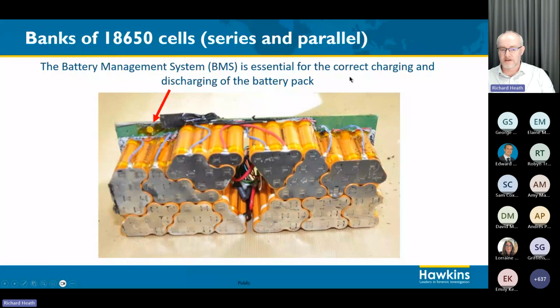And a larger example here, this was taken from a hoverboard. And what you have here, in order to get more power out of the battery pack, you have a number of groups of lithium-ion cells that have been connected together in parallel, and then the groups are connected in series to give you an increase in voltage. So you get both the higher voltage and the high capacity that's needed by the drive system for the hoverboard. And in this case, the large PCB in the back of the picture is providing the battery protection function.